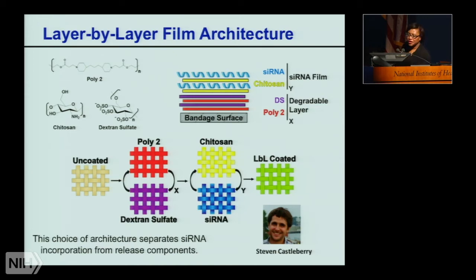And I apologize, it looks like there's a little disconnect with my computer and the screen, but what you're seeing here are the same components we talked about before, a degradable polymer, poly2, and here we used chitosan, which is positively charged and not degradable over short time periods, and dextran sulfate, another natural sugar. And the way we composed these films was essentially to build an underlayer of dextran sulfate with this poly2, and then on top of that, layer siRNA and chitosan.